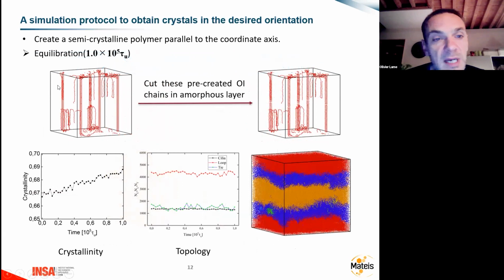So we let the system crystallize with these nuclei, and afterwards we cut the chains in the middle so that it doesn't strongly change the topology of the system. And of course, the crystallinity is increasing. Again, we can measure the number of loops, cilia, and tie molecules, which here seem to be much more constant because the crystallinity grows very, very quickly. Then we obtain at the end a beautiful lamellar system, which is perfectly oriented in the Z direction. And now we can begin to compare different ideas or different systems. The first thing we have done is to perform this kind of modeling with the 3 systems I showed before, with 200 beads, 300 beads, and 500 beads per chain.